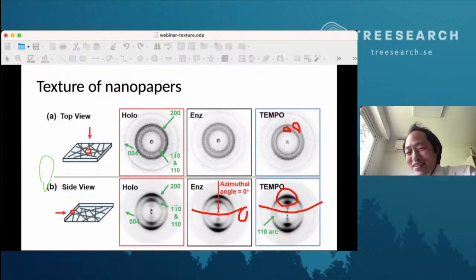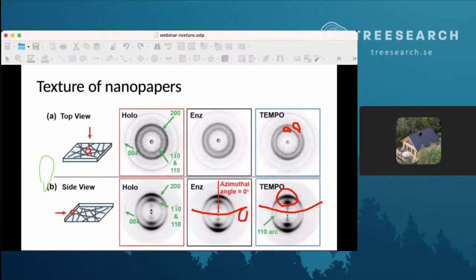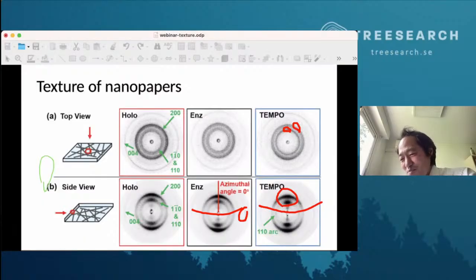Okay, so I think the concept here is not that to expose it, but in general, when you make cellophane, you dissolve it in an aqueous system and regenerate it in an aqueous system. So the first molecular association is due to the hydrophobic interaction, and it is never meant to be exposed to other stuff during the regeneration. The growth direction of the structure in this regeneration process is along the direction of what we call hydrophobic interaction. So in the case of cellophane, it's really strong, and it's always what we see in regenerated cellulose because it is predominantly growing in that direction.